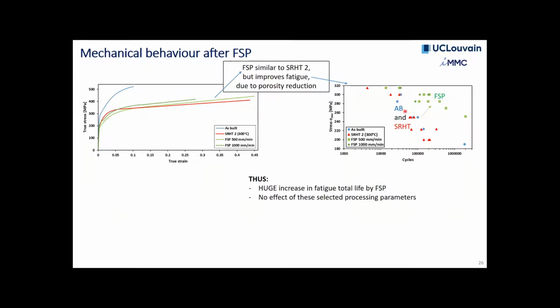So these ones are, let's say, not so great. And they're influenced very significantly by these porosities, as I've shown you previously. And then you have the friction stir processed materials here, and you see they have a very impressive increase in fatigue life that can go to a factor of 100 for some loading conditions. So, a huge increase in total fatigue life by friction stir processing, and no effect of these selected processing parameters.